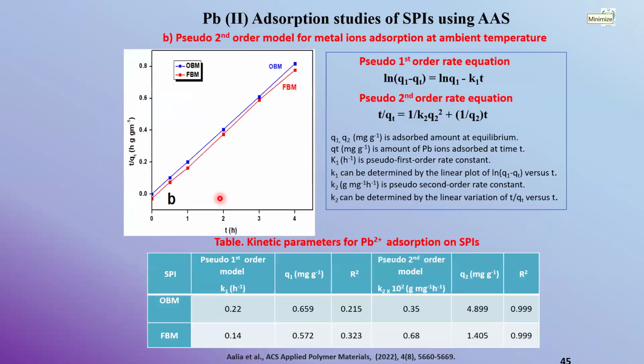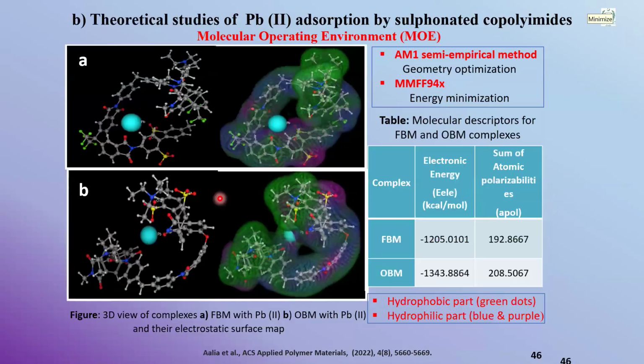These were some of the calculations for the pseudo first order and second order rate equations. And here also we performed some theoretical studies for the oxy and fluorinated dianhydrides. So here you see with the oxygen containing dianhydride, you get the electron energies which are more negative, which means that these sulfonated polyimides made good bonding with the lead too. So most of the lead can be taken out from the water with this dianhydride as compared to the other.